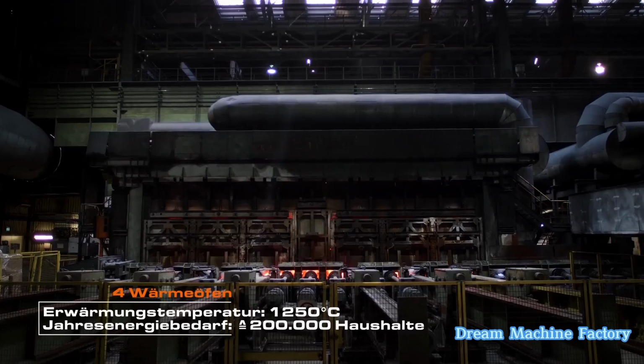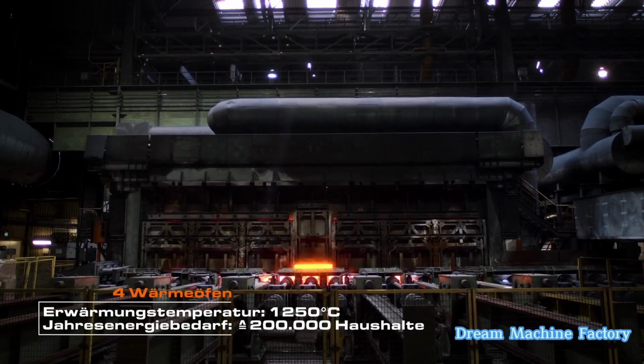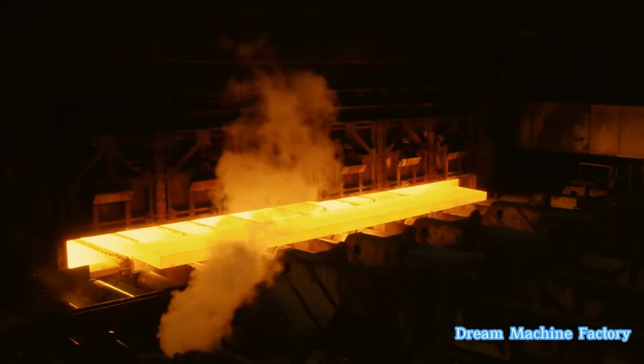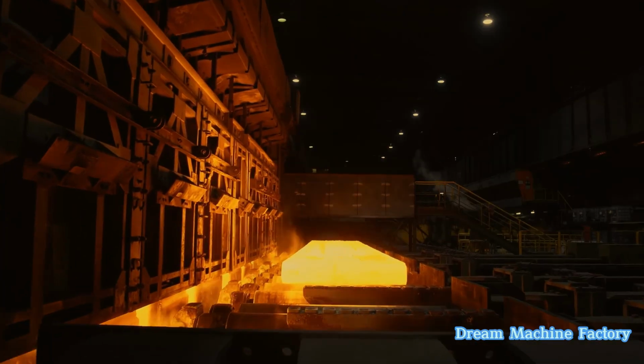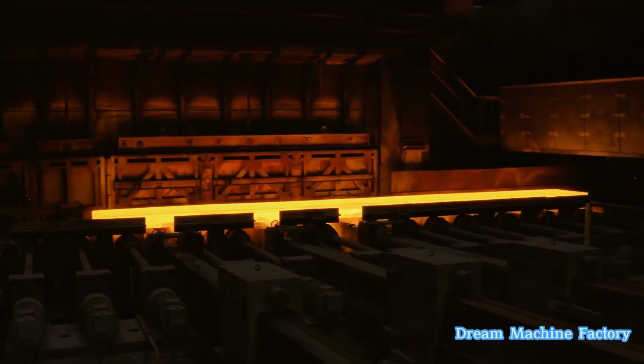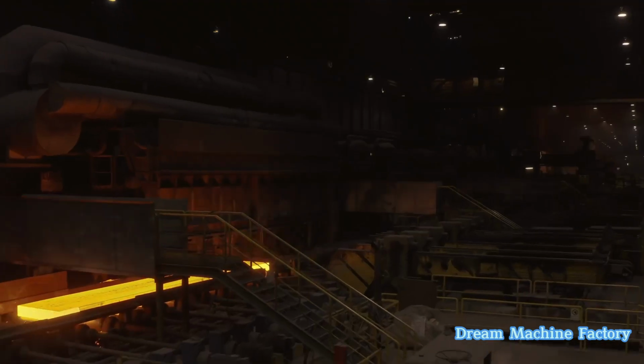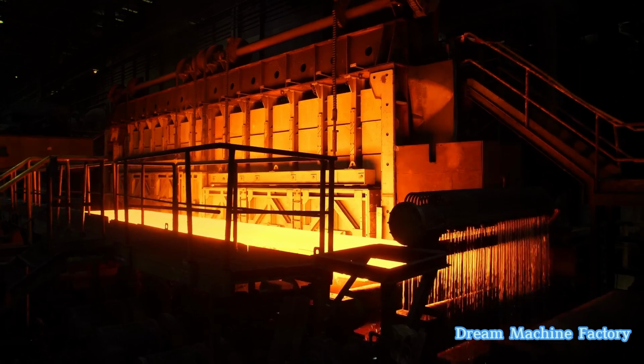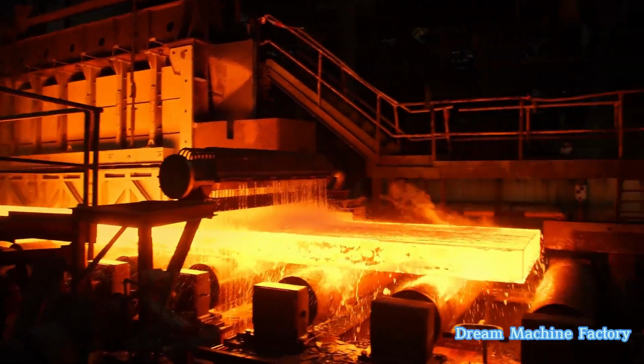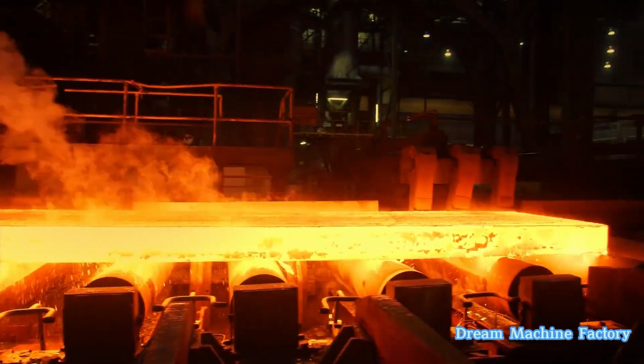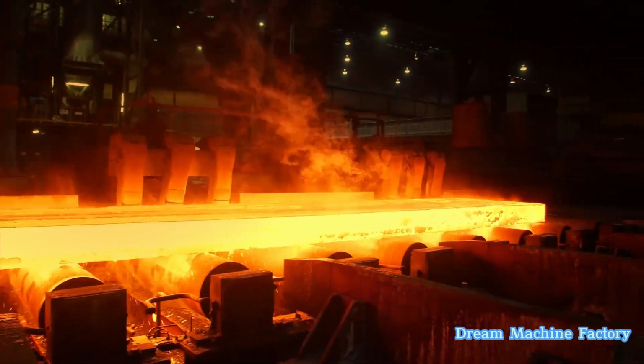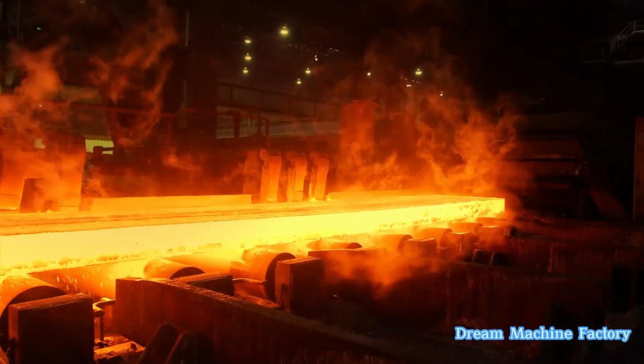The slabs are fed into one of the 4 heating furnaces, where they are heated to a temperature of 1,250 degrees Celsius. This high temperature softens the steel, making it malleable for further processing. The energy required to heat the slabs is significant, consuming an amount equivalent to the annual energy needs of 200,000 households.